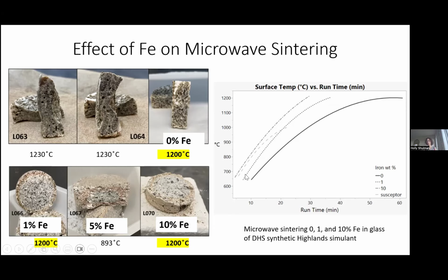And then you see at 1% still very vigorous heating, and we're getting to less than 40 minutes to hit that 1200 C. So then my student, this was a BS thesis student, his name is Jay Stearns, and he actually is a full-time employee at Corning Glass, and they sent him over to do his BS with us at Alfred University. And he was really puzzled when he saw what these samples look like. With 0% iron at 1200 C, we have a really solid, strong sample. And all of these iron-based materials were still friable, with the 1% iron actually being harder than the higher iron content.